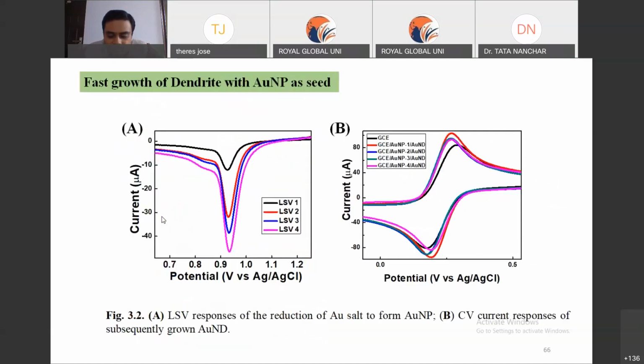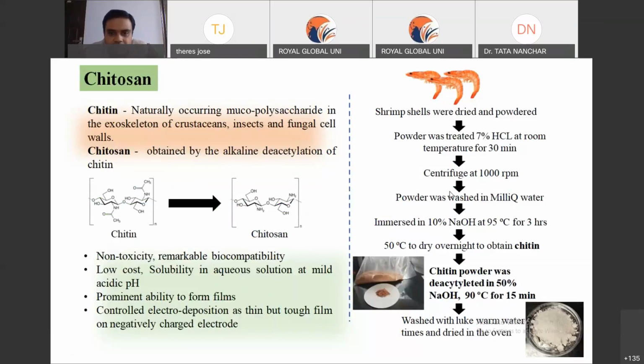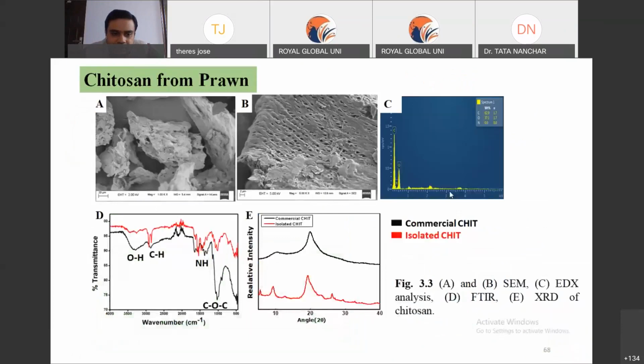We developed the sensor system by forming nanoparticles onto the surface. You can see the formation of the gold nanoparticles, where the current keeps on increasing on the y-axis, which means the conductivity is increasing. Similar data is shown here as well. This is the method we followed for developing the chitosan. We used shrimp shell in this case, and this is the characterization of the chitosan from prawn. This is the commercially available chitosan, and this is our lab-prepared one, the red curve in both cases.